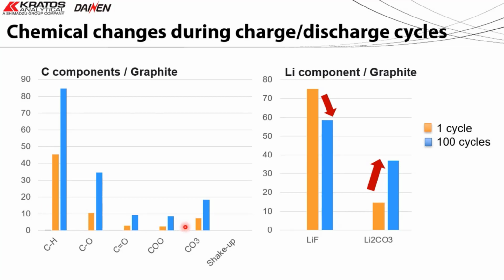And if we look at the lithium components, they're increasing relative to our as produced sample. So both of these are positive, significantly increasing the lithium fluoride. But the relative amount of the lithium fluoride in particular decreases with increasing cycle, and we get more of the lithium carbonate.